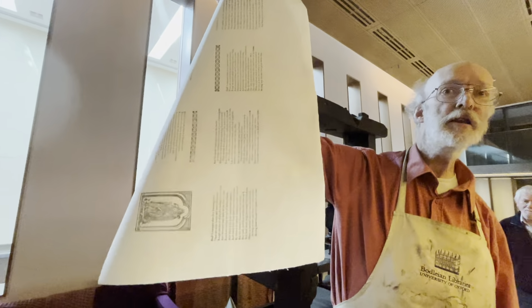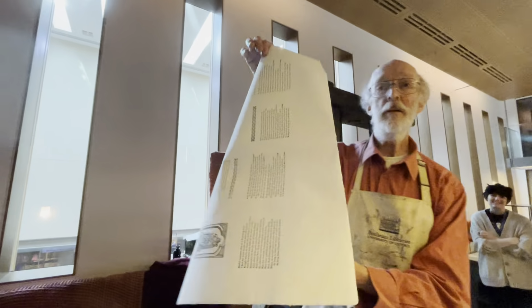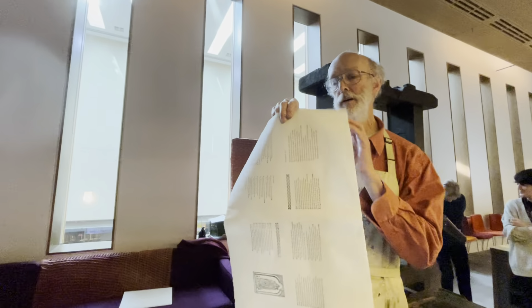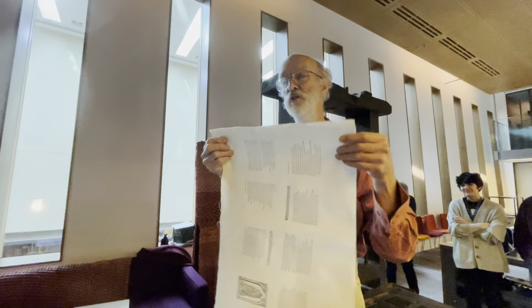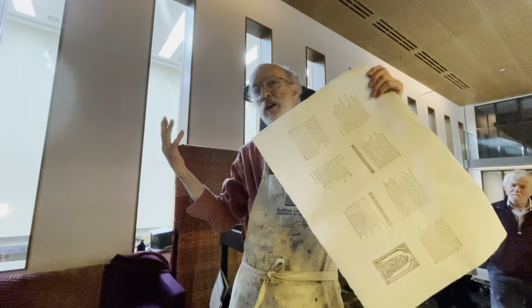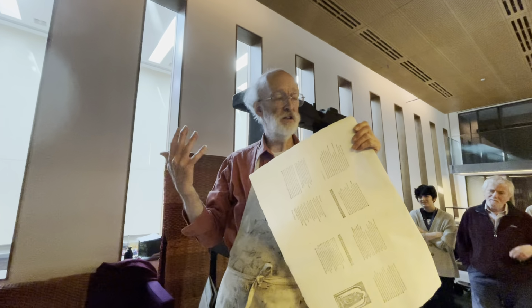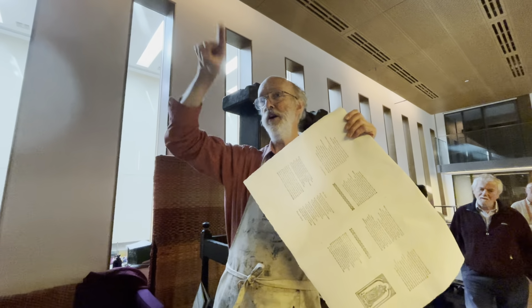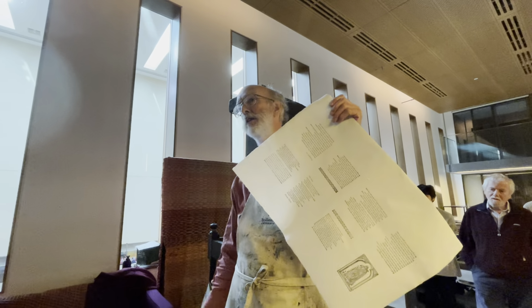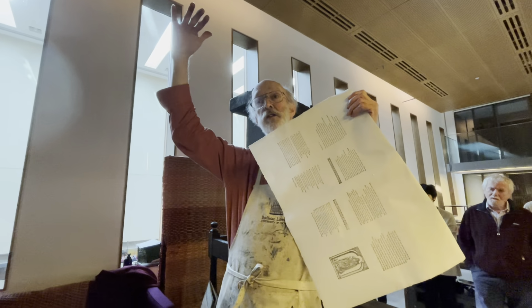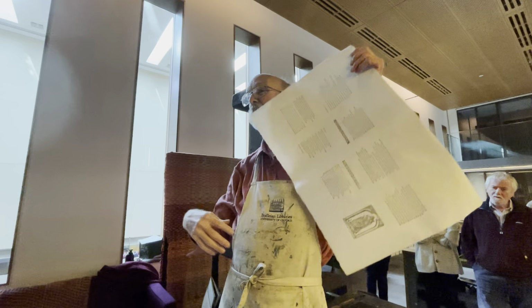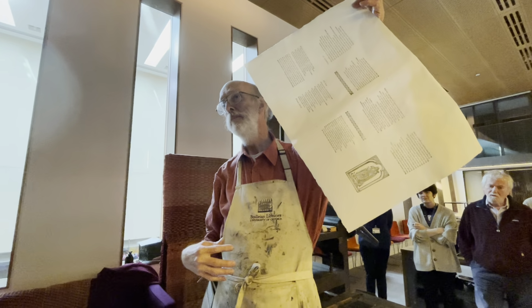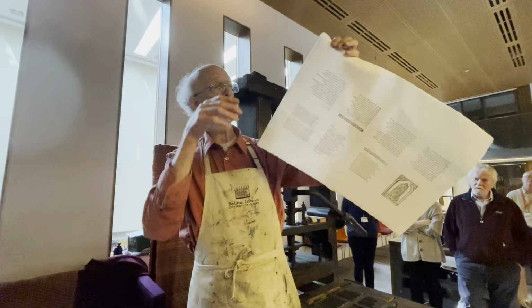This is why you dampen paper. I've read all sorts of explanations of why you dampen paper. You dampen paper so that you can get to the pub sooner. It makes the printing easier, and there's all sorts of spurious explanations of why. You know, paper is more receptive to ink and so on. The simple material scientist, engineer's explanation is if you look at a sheet of paper under a microscope, it's a series of hills and valleys across the surface. To get a continuous black, you have to squash the hill down to the level of the valley. Make it damp, it's easier to squash. That's it. So, that's a demonstration of printing.